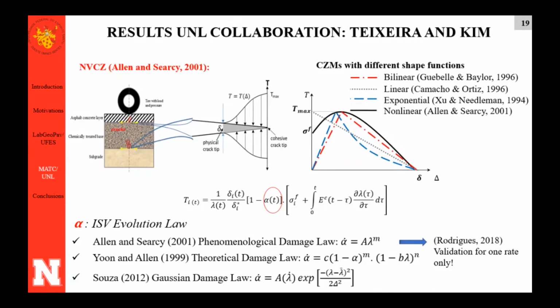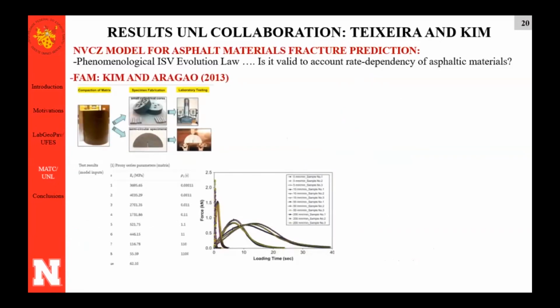So I need to verify, what if I change the rate? Can I still use this model? To verify that, we start by looking at one study from Kim and Aragao, published in 2013, where they had the fine aggregate matrix behavior at different rates. So this is laboratory data available for us, anyone can use. And they had the linear viscoelastic properties there. So I could use that to verify if the model that I'm proposing as the best one to predict crack initiation and propagation in asphalt is suitable as a rate-dependent model.